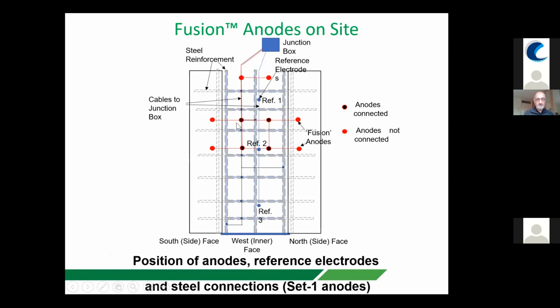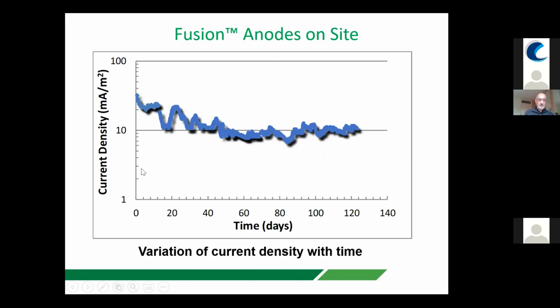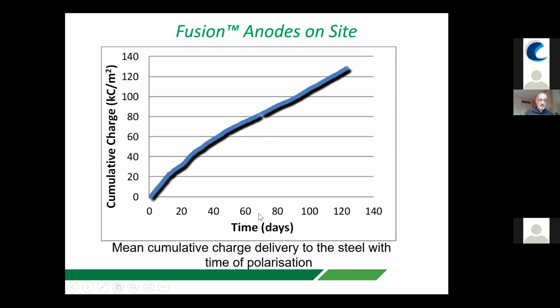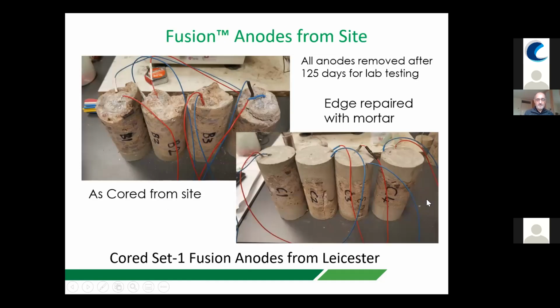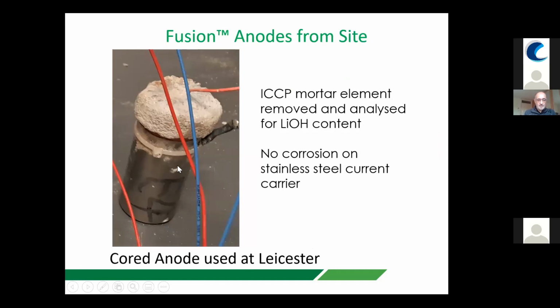Initially, we only connected the 4 anodes in the middle because we wanted to take some anodes out. In fact, we took all the anodes out eventually to see what happens once you put them in concrete. We maintained quite a high initial current, and the cumulative charge the first stage, we went up to about 130 kilocoulombs. So that took about 120 or so days to deliver. Then we took the anodes out, cored them out, and sort of fixed them, if you like, put them in a sunbox, and continued to. You can see that the stainless steel remained intact, which is one of the reasons we took them out.